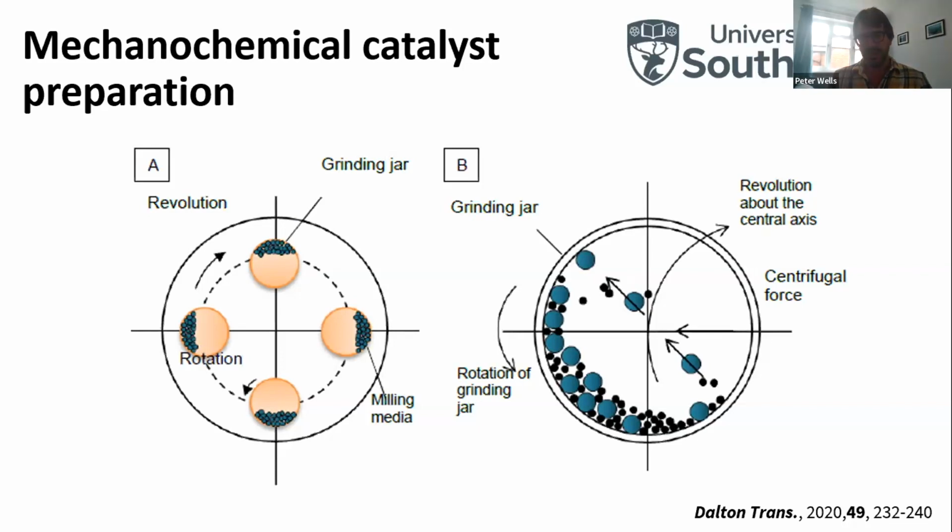And so in terms of mechanochemistry, it offers a really interesting route to make materials and produces far less solvent waste. So there's quite a drive in the industry to do this. So in Rachel's work, we were looking at planetary ball milling. So here we can see a picture of that setup of the actual planetary motion and the individual jars and how they rotate. And within each jar, a series of milling media and your catalyst. So in Rachel's work, what Rachel was looking at was the production of perovskite catalysts, specifically lanthanum manganese oxide.